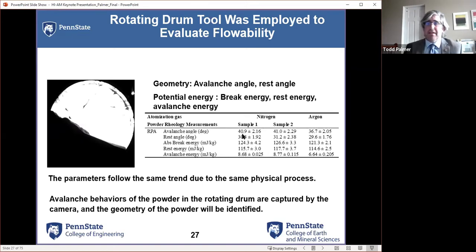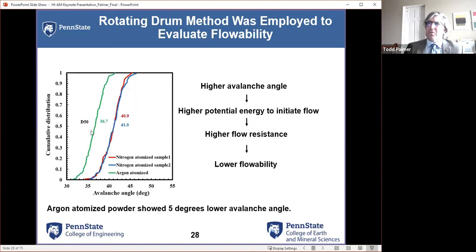And what we tended to find here is that this simple test, basically rotating a drum and measuring this avalanche angle, was actually pretty good at finding a difference between the powders. Really, the argon powder with a lower avalanche angle shows better flow characteristics than the two nitrogen powders. Now, we definitely see that when we apply that as a cumulative distribution. And so higher resistance, lower flowability. This is a pretty significant difference in flowability.